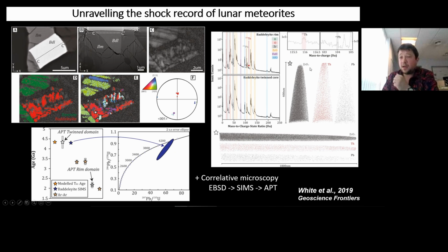We couldn't measure uranium, but we did get thorium. So we got a nice peak of thorium-232, double charged at 116. And again, we got lead, obviously 208, double charged at 104. And that allowed us to calculate the thorium-lead age for these samples. So no obvious variation within them. So again, this is a massive data set, but boring, unfortunately. But we got a really robust thorium-lead age as a result of all those counts.